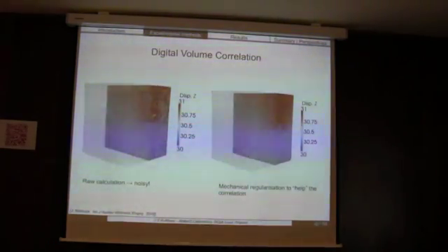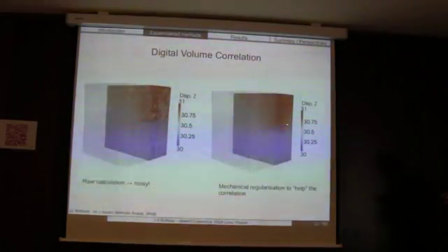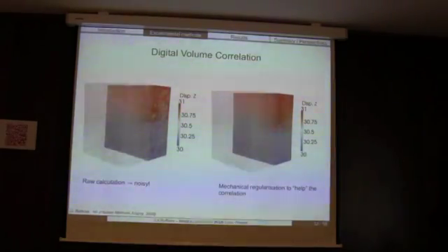So to help out the correlation, we resorted to mechanical regularization. That's to say, you will take a narrow zone around the crack where the correlation will give the displacement field. And in the other region here, it will just be driven by the mechanics.